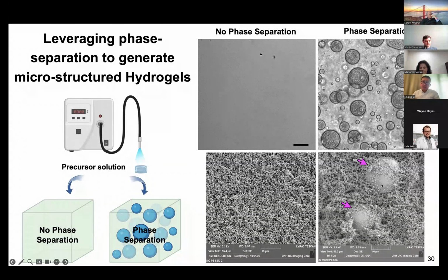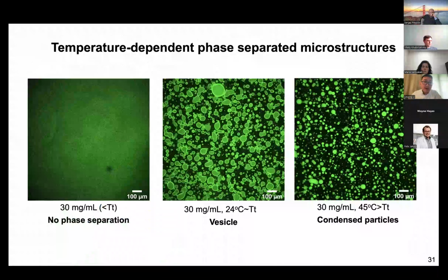embedded. So this is something different from what is currently the granular hydrogel, because those granular hydrogels essentially anneal the particles together. So in our case, we not only have the particles, but we also have a secondary network. So essentially, we made a composite hydrogel that features these phase-separated domains that are crosslinked within the matrix. So there's a slight difference between the two categories of materials.